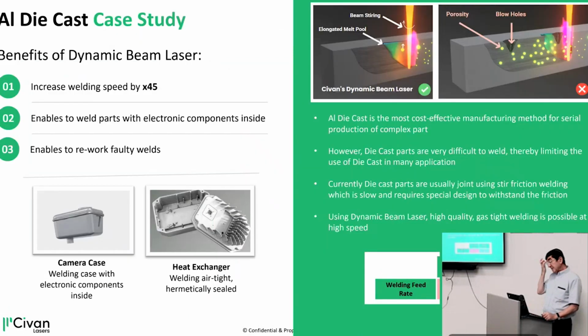The other example is die-cast material, as I mentioned in one of the examples before. When you weld die-cast material, all the gas that's absorbed boils and creates sputter and porosity. But we can manipulate the beam and go a few thousand times inside the melt pool at a very high feed rate and basically get all the gas out without having blowouts. So we demonstrated several of these products.